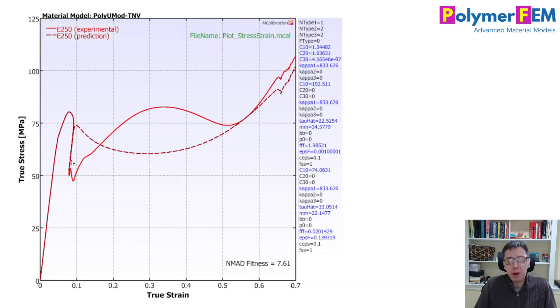It's a multi-axial stress state that changes the response. You can't in this case predict the actual stress at that point using this material model without having more information about the multi-axial nature of the deformation at that point. Pretty interesting. This difference is much larger than I initially thought it would be, and it's kind of interesting because it has influences to what we do with this kind of situation.